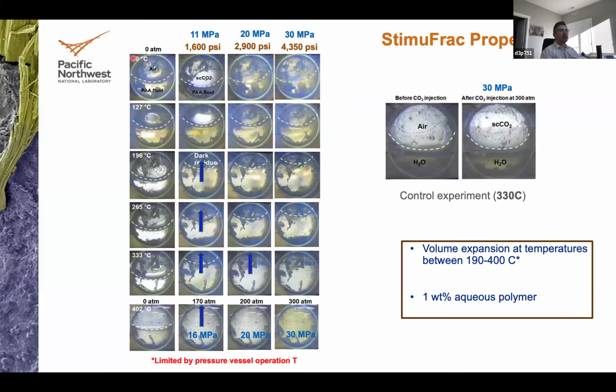And then at ambient temperatures, it doesn't matter how high the pressure of CO2, you will not see the volume expansion of the fluid. But as you go higher in temperature, you start seeing that at pressures of CO2 as low as 11 megapascal, this is about 1600 psi, some changes in the volume. So you still have basically the coexistence of a supercritical CO2 phase, but the volume of the polymer is expanded by the reaction and the CO2 getting into the solution.